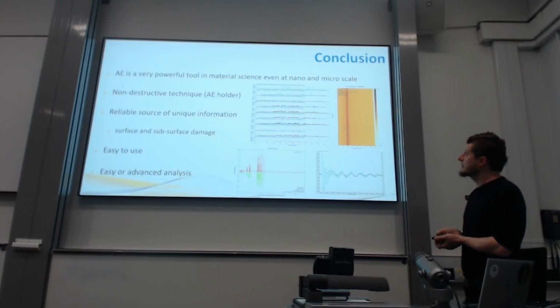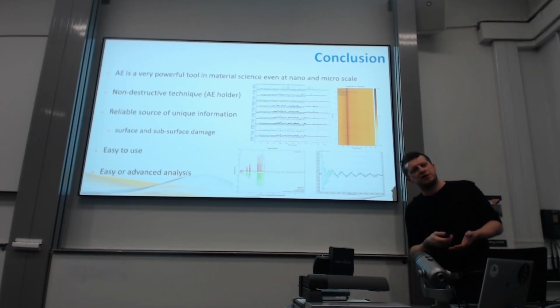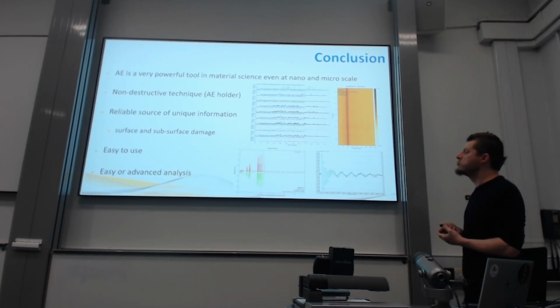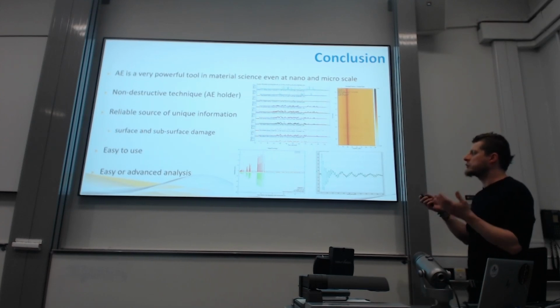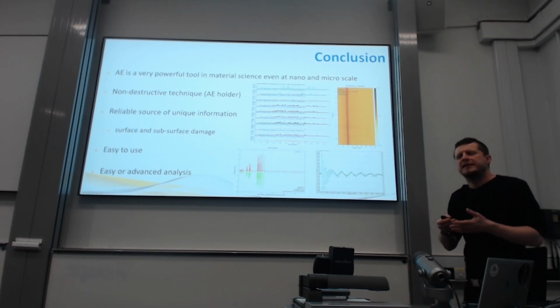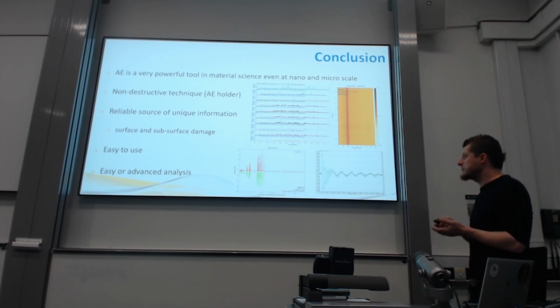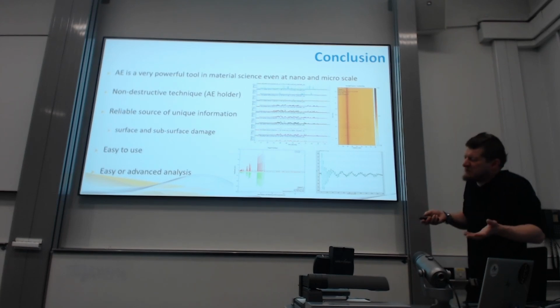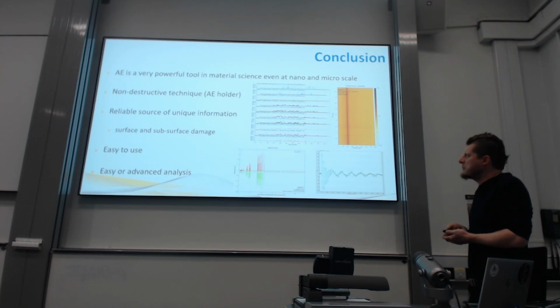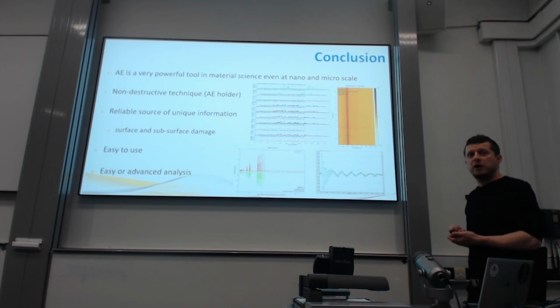So at the end, acoustic emission is a powerful tool, standalone or in combination as a multiple sensor approach, that can be used for different types of coating. No, not for all of them: very ductile samples cannot be measured, because ductile samples do not produce acoustic emission. But it can give you mainly damaged subsurface information, which is definitely important for surface and local mechanical properties.